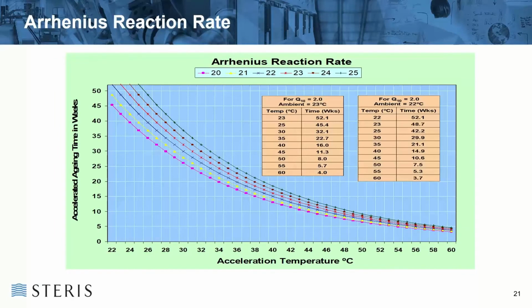This is a chart I did up a number of years ago to depict the different temperatures versus aging time in weeks. So basically, on the left-hand side you have the time in weeks, and down the bottom you have your accelerated aging temperature in degrees centigrade. So if you take typically a 22 or 23 degrees ambient temperature, a year will take approximately 52 weeks. Whereas if you increase that temperature, say with an ambient temperature of 23 degrees, that 1 year will be reduced to the equivalent of 4 weeks at 60 degrees.